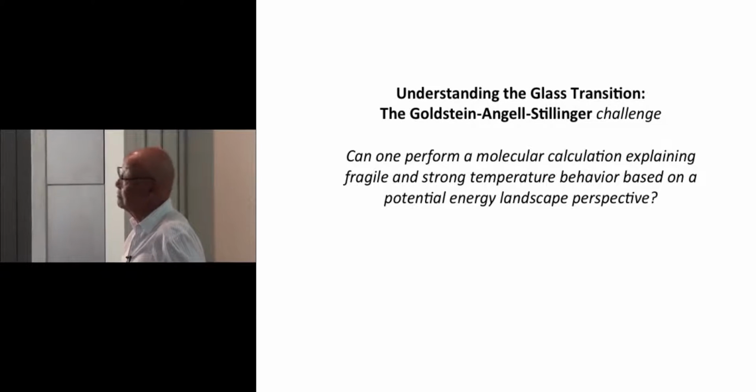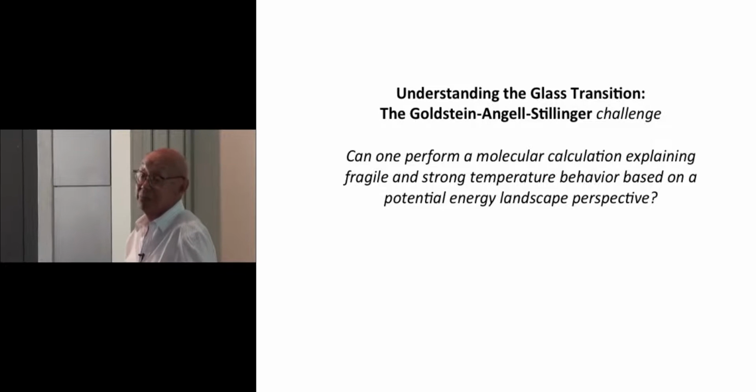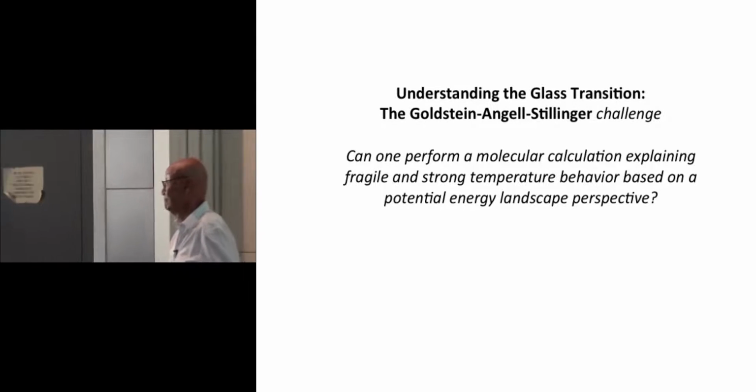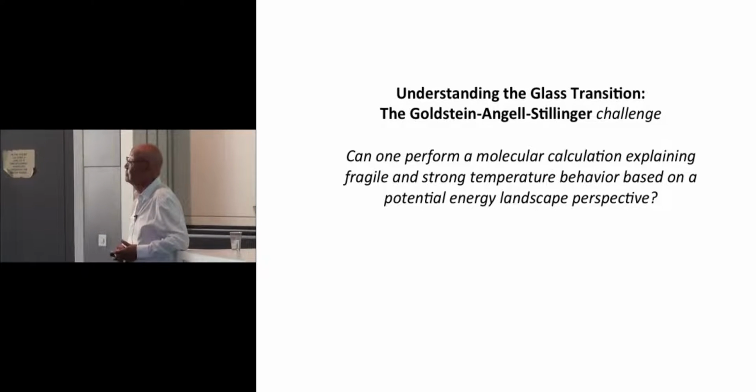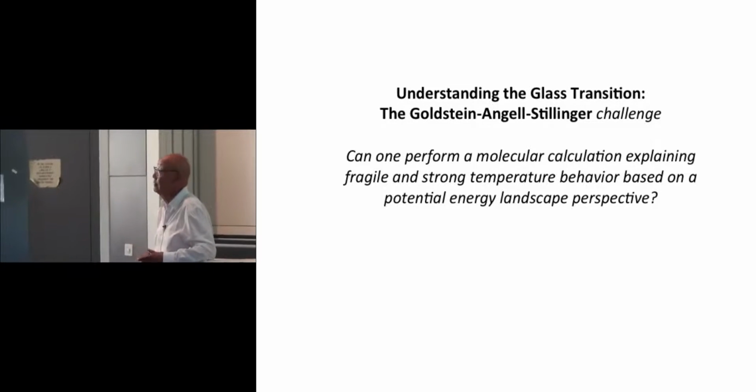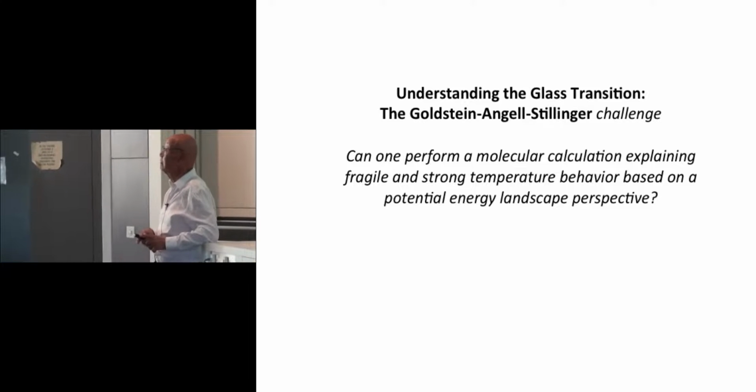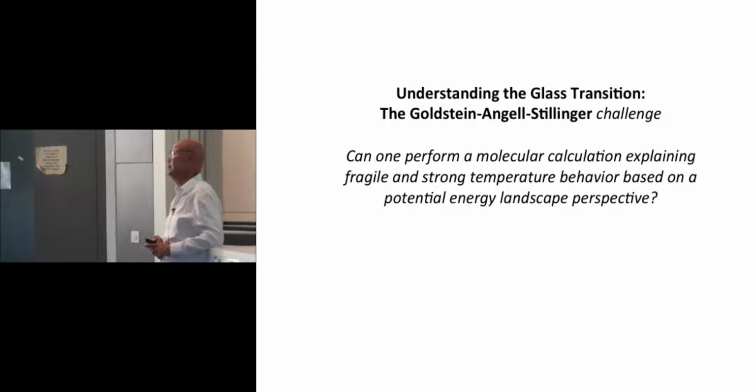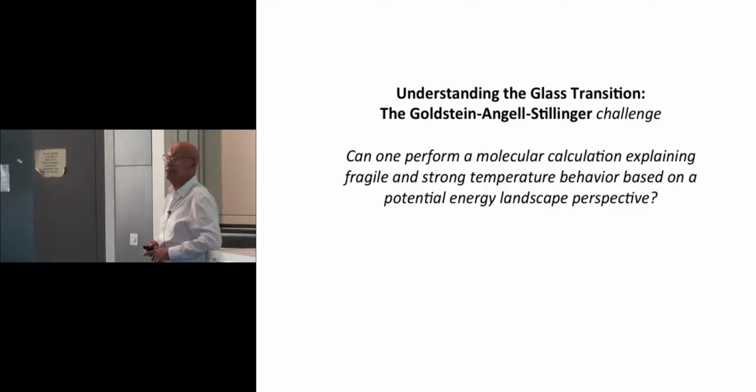in which we calculate the viscosity in terms of a temperature-dependent effective activation barrier, treated like an activation process. We already knew that, people have been thinking about that. Now that calculation has been done for both the fragile and the strong liquids. Two separate calculations. You can compare them afterwards. Okay? So in that sense, it's a systematic calculation of these two behaviors.